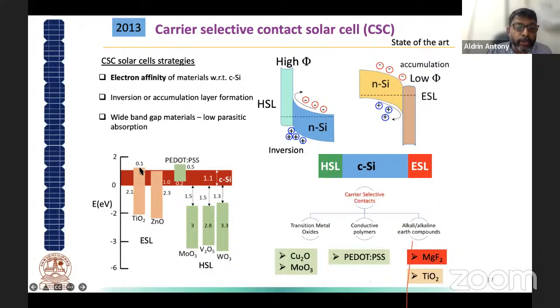So there is only a 0.1 difference in the electron affinity level, and that is why titanium dioxide can form a very good electron selectivity, because it is almost at the same level as the conduction band of crystalline silicon. It can act like a very good electron transporting layer, but it can block the holes coming in this direction. Similarly, zinc oxide can also act like an electron transport layer, and it can also block the holes.